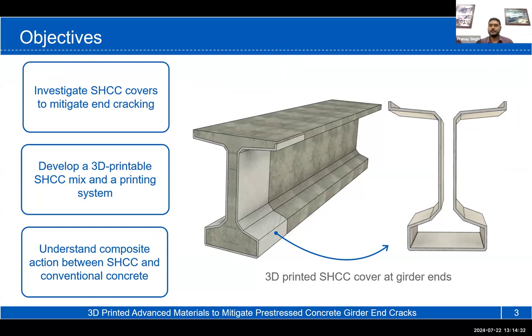Pranay, just to go back to Samir's previous question. So this is not for transferring the load that is coming from the columns. It is just after the moment you release the pre-stress from the pre-stressing strands. So the girder is still in your precast plant, and the moment you release all that pre-tension load from the strands, it is transferred onto the concrete. And because of that, the transfer distance is very short typically. And because of that, the concrete has limited tensile strain capacity, and this end cracking develops even before the girder is taken out of your pre-stressing bed sometimes. So that is the cracking that we are addressing, not the cracking that is coming onto the overall structure of the beam. Yes, now go ahead, Pranay.